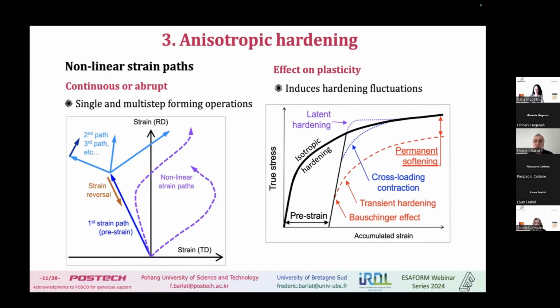So I showed here a true stress strain curve with the isotropic hardening, the conventional hardening curve. But if we do some pre-strain and reload, we may do some reverse loading. We'll get the Bauschinger effect in red here. Or we can do cross-loading. Cross-loading being, for instance, tension followed by tension at, let's say, 60 degrees. But it can be other possibilities like tension followed by simple shear and so on. And with cross-loading, we can reload at a lower stress, a little bit like the Bauschinger effect, and then recover the stress strain curve. Or we can overshoot the monotonic curve like here.